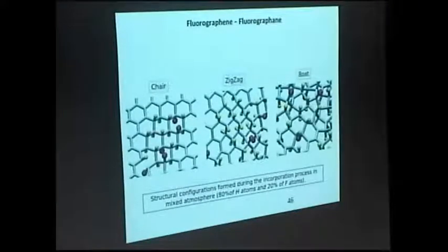We also found, and this was quite interesting, some specific configurations. Here, yellow are hydrogens and red are the fluorines. We saw some specific organization of these atoms on the graphene membrane. And these configurations were confirmed later using DFT. It's a case where things were inverted, right? Instead of DFT telling us what the structure is, and then we confirm that we can reproduce it, we found it first and then saw in DFT that it was true.